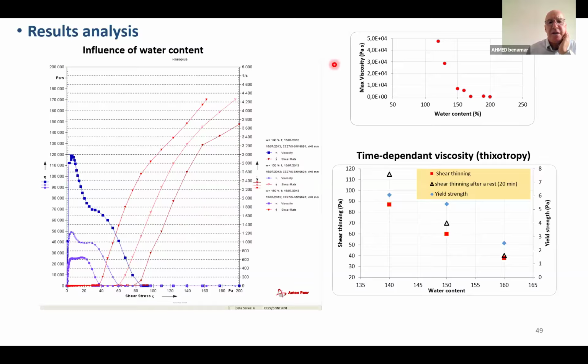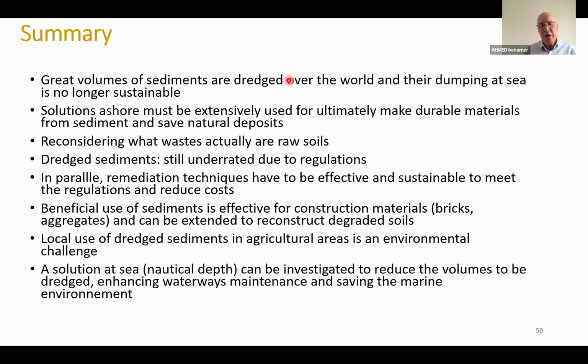In another study of the rheological behavior of sediments from the port of Le Havre, we show that for different situations there is shear thinning before rest and after rest. So in different conditions, the rheological response of such material is different, and we see here that the viscosity was decreasing when the water content increases, and this kind of material can show thinning characteristics during the test. Okay, I finish by summarizing all the results I showed.